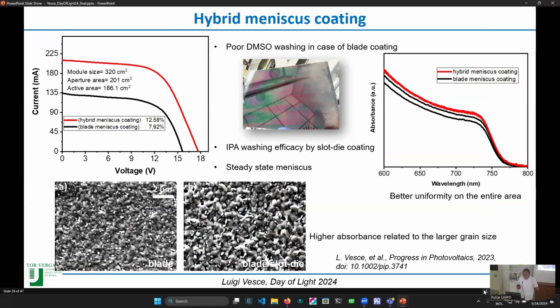So first we try to deposit on such a big substrate just by blade. We deposit both the perovskite and the anti-solvent by blade. We got an efficiency of less than 8%, and it's easy to understand also from this picture. This is a good perovskite, this is a bad perovskite. Just to inform you, because of the blade coating technique, we cannot guarantee a steady state meniscus. Meniscus is the gap between the blade and the substrate for the full substrate.